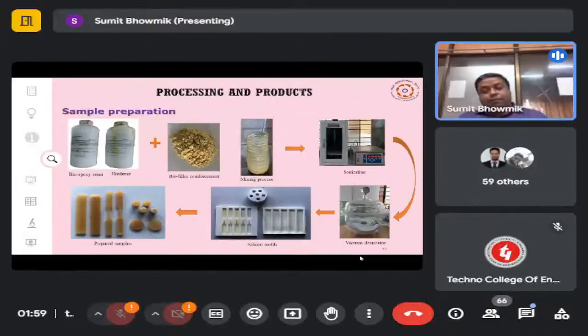Then, due to the sonication, some voids are generated in the composite which need to be removed. For that, we use a vacuum desiccator or vacuum chamber to bring out all the voids inside the sample. Then, as per the testing requirement of the sample, we have to make the molds, and the sample has to be prepared.